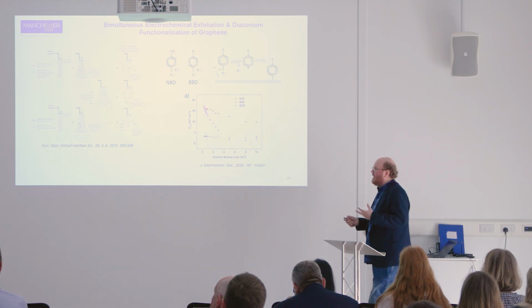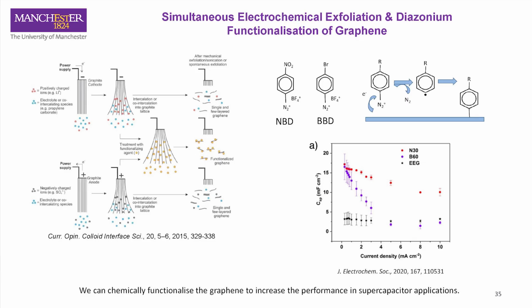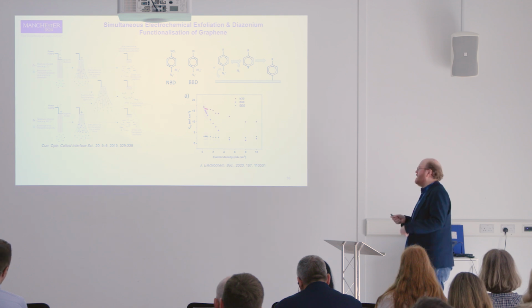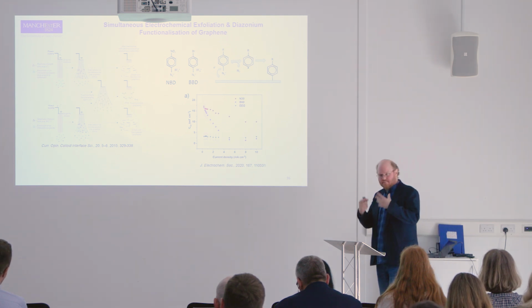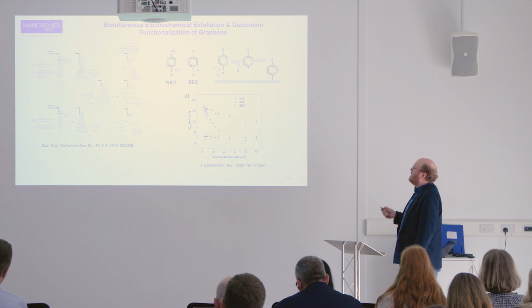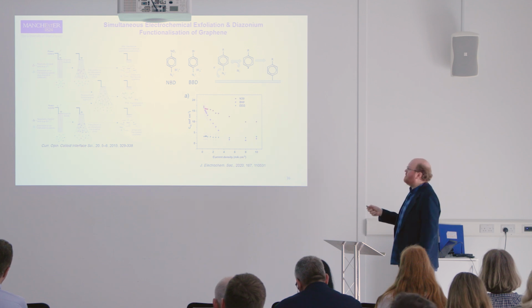We can take that a step further and deliberately do additional functionalization with other molecules during the exfoliation. So we do the standard electrochemical exfoliation where we have our graphite in solution. We normally have an electrolyte which has, say, a sulfate ion in there. But we can also have some aryl diazoniums. Aryl diazoniums are molecules that very rapidly react with sp2 carbon, like graphite, graphene, nanotubes, things like this. And that allows us to have these aryl groups on the surface, which again are going to prevent that restacking, but also introduce other functionalities. So we can have a nitro or a bromo group to get that added pseudo-capacitance.